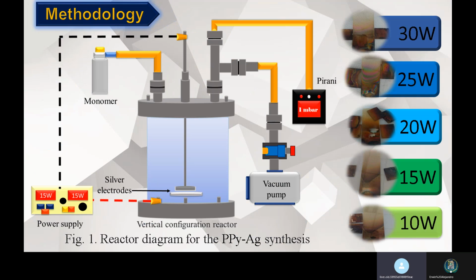In the methodology of this work, polypyrrole with silver was synthesized by plasma, with polymerization and simultaneous ablation with direct current charge from 10 to 30 watts. Polypyrrole was polymerized in gas phase with silver ablation taken from silver electrode. Morphology, chemical groups, elemental analysis by XPS, absorption and reflection were investigated.